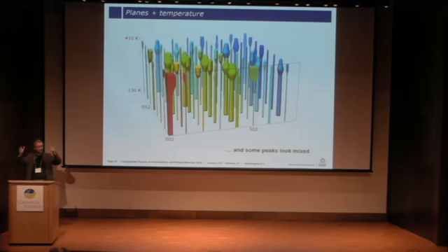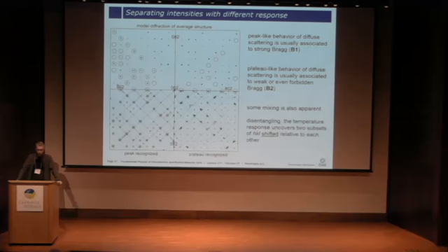they stay expanded. And if you go away to the inside of this construction, to low symmetry directions, to low symmetry peaks, you see that some of them do expand, then shrink slightly, but not to the initial diameter, which means that these peaks are somehow mixed. Well, to separate peaks with different intensity response manually, I'm too lazy, so I calculated some functions which do discriminate somehow semi-quantitatively these two cases.